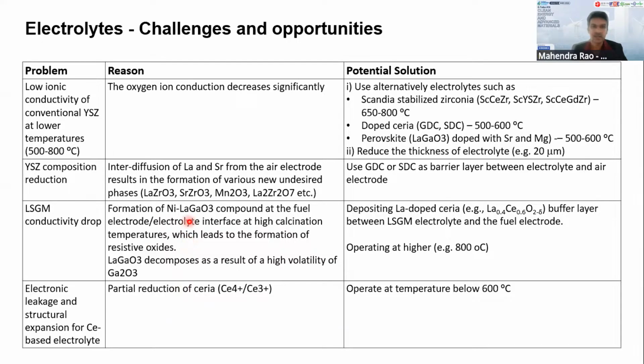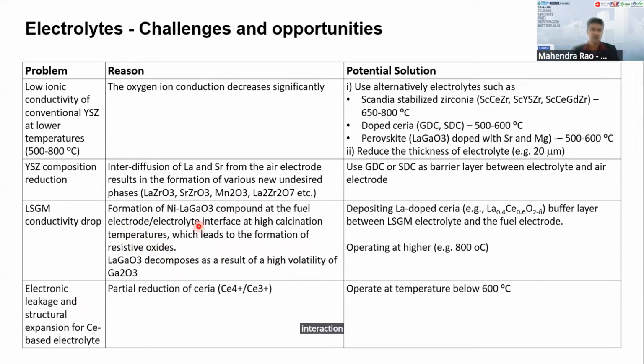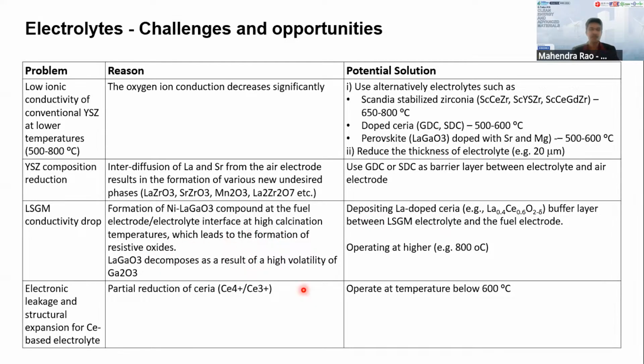And LSGM, you know, is a well-known material. However, there is the chemical stability issue when it can form a nickel lanthanum gallate phase when you operate at high temperature. This is what we call the interface interactions. So this will decompose. It will change the composition ratio of this electrolyte material, and eventually it will reduce the conductivity of the LSGM. So this material is very good in terms of conductivity, but again, as I said, the stability and the durability of the material are very important for long-term operation.